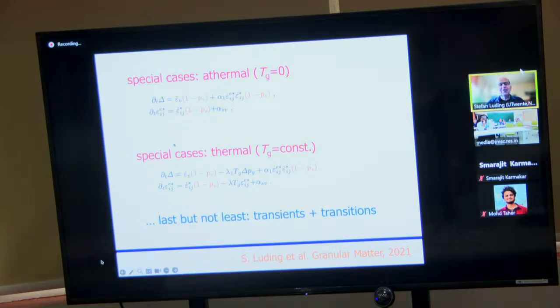For the warning. Okay, so if I want to understand a continuum theory, then I will take special cases. So the first special case is athermal. So I set Tg equal to 0, and that gives us a very simple subset of equations with which we can analyze. Or you can set the temperature to a constant that also drops out the evolution equation of temperature. But this is more related to thermal systems like glasses, as my previous speaker mentioned, or polymer melts, as I mentioned in one example before. Athermal refers more to granular materials because in many situations they are really athermal and the granular temperature can be ignored. Okay, and then you have everything in between those two, like transients and transitions.